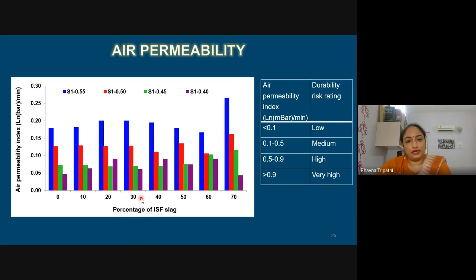Okay, so let me again come back to the topic, air permeability. This was conducted using the Autoclam permeability index, which is more useful for knowing the permeability of cover zone concrete. The test results show that permeability of only the 0.55 water cement ratio was more than 0.1, and the 0.50 water cement ratio. There were two water cement ratios, 0.55 and 0.50, which had permeability of more than 0.1.